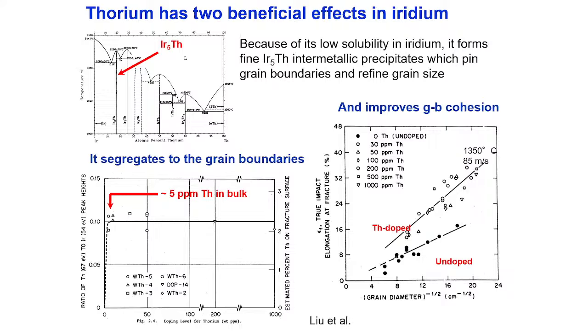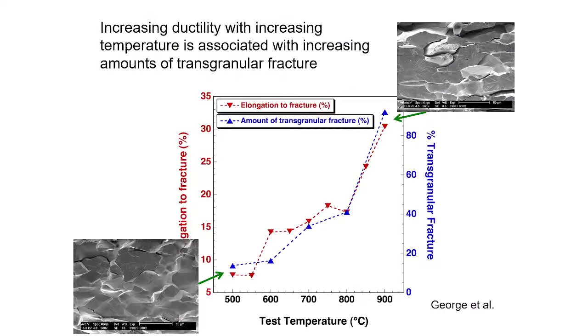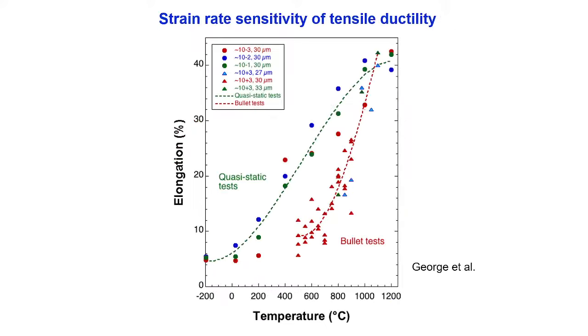And as I said, it suppresses the grain boundary fracture. Down here you have mostly grain boundary fracture, and as you go through this ductile-brittle transition, it transforms from mostly grain boundary to mostly cleavage transgranular fracture. So suppression of this grain boundary fracture is the reason you get this thorium effect. Then you can put all this together: if I look at all the quasi-static tests at 10 to the minus 3, and all the bullet tests at 10 to the plus 3 per second, you can see the dramatic shift in the ductile-brittle transition.